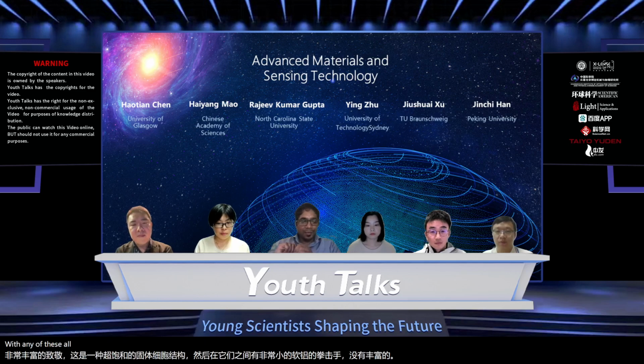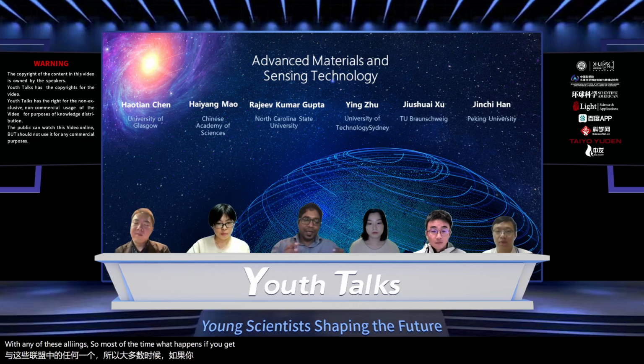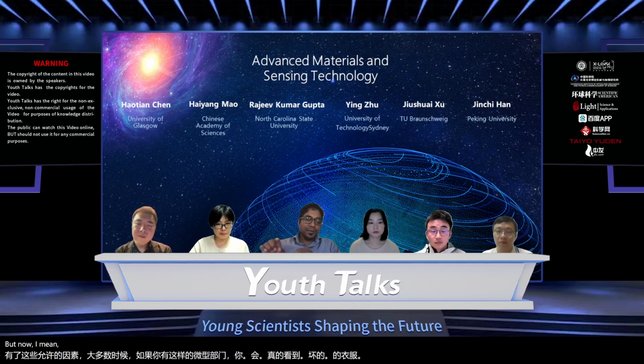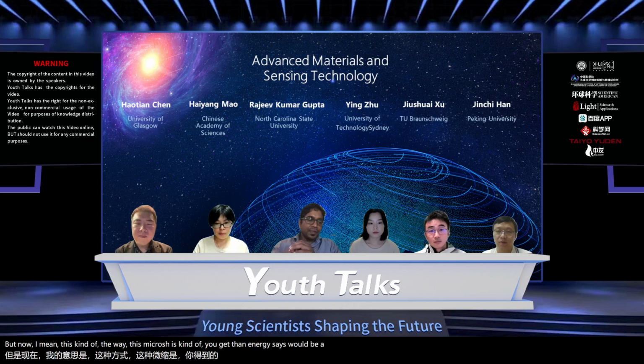of these alloying elements. So most of the time, if you get a microstructure like that, you would see really bad corrosion. But now, the way this microstructure is, you get good corrosion resistance, and these soft phases hopefully would give you a good fracture toughness and things like that.